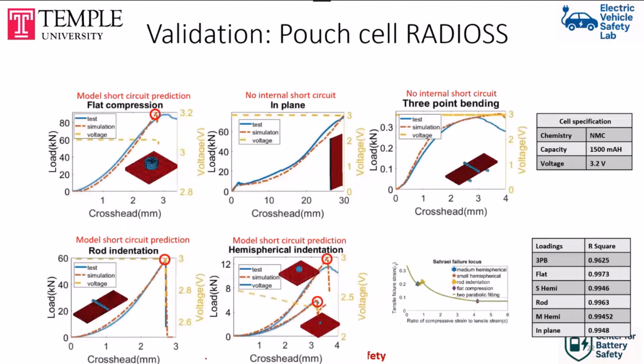So once we implement that, this is now the result that we validated for a pouch cell. Under all of the different loading cases, the places with red circles are the places where we identified a short circuit. For all of the cases that had a short circuit, we predict the short circuit at the right location. And the cases where you don't see a red circle are the cases that didn't have a short circuit in the test, and our model also did not predict a short circuit for those cases.